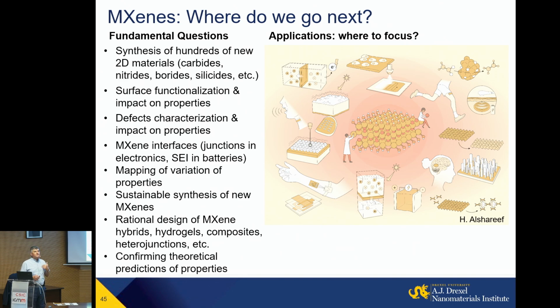There are many physical properties predicted by DFT, not confirmed. Two-dimensional ferromagnetism, antiferromagnetism, chemically tunable. Chemically tunable superconductivity has already been demonstrated for niobium carbide, and depending on functional groups, they can be superconducting or not.